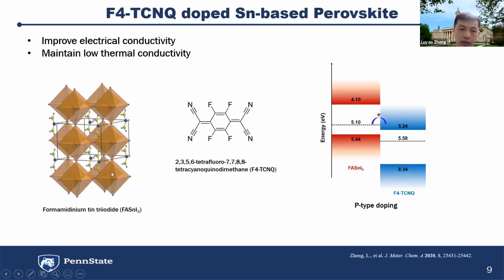So basically, we want to get a higher electrical conductivity and try to maintain low thermal conductivity. So we picked FASnI3, formamidinium tin iodide. It's tin-based, probably having a high intrinsic electrical conductivity. And we have this FA cation on this side. It has more freedom compared to the cesium because it has a degree of freedom to rotate or twist. Probably even better than the cesium, it will give us even lower thermal conductivity.